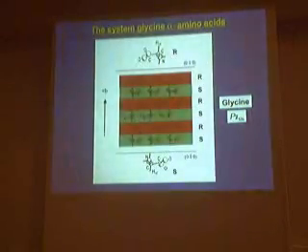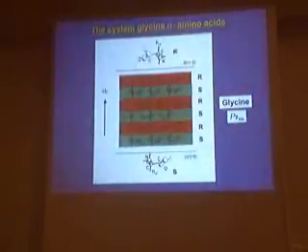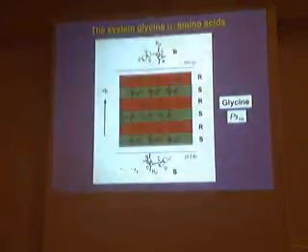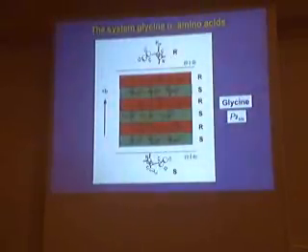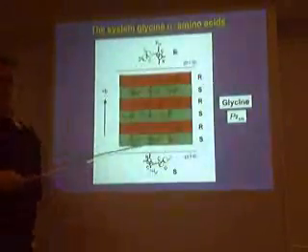It's stable, but doesn't appear in water. You have to have special conditions, high pH, low pH. But if you crystallize glycine in water at room temperature, and pH 5 to 6, 7, you always get the alpha form of glycine. Okay? Now, I discussed the aspect of reduction in symmetry in crystals. Okay? So let us analyze the structure of this alpha glycine crystal.